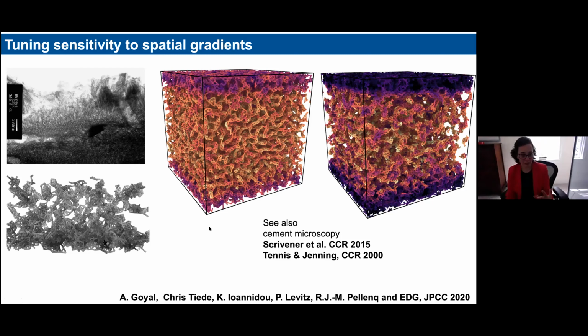And then we can study the interplay between these spatial gradients and the evolution of these interactions. So here, these are two snapshots of the simulation that correspond to the same type of interaction that I showed you before. These would be early stages of the hydration, and these would be later stages of the hydration. And they are colored in terms of local density. And so you can see, and this is the case in which we have a preferential precipitation of the material starting from the surface of the grains, which are mimicked as the boundary of our simulation box.